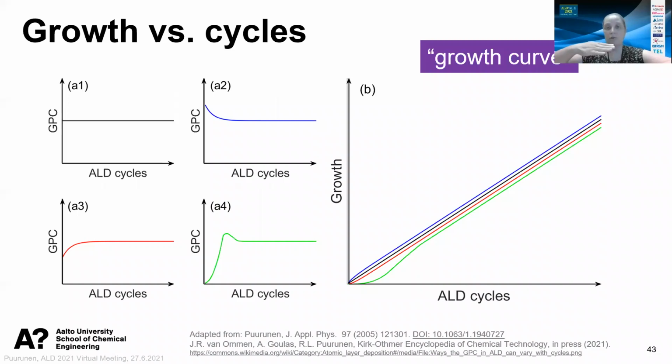So when you start growing on one material, the amount chemisorbed in metal atoms per unit surface area can be very different for the substrate than for the material that you're actually growing. So aluminum oxide starting on silicon, for example, and then ending on aluminum oxide, you can have these differences in the beginning before you settle to a constant value, and that's all normal.